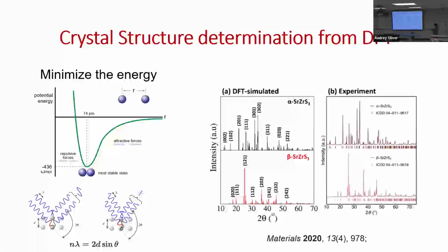Okay, so let's see some examples. We can determine crystal structure. We can calculate the energy as a function of distance, right? You are just minimizing that energy, and you can find the binding energy, so your structure. This is an example for the hydrogen molecule. In principle, it's pretty similar for all solids. You change distance, you move atoms, track the energy, and find the lowest energy. Then we do that for solids, and we can use Bragg's diffraction condition for different planes and find out those diffraction peaks. These are DFT simulated, and this is experiment. And once you have the correct structure, you can simulate these experimental patterns.